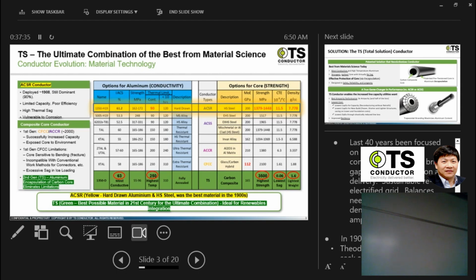And the other issue related to this limited stretching is it is a very delicate material that you have to manage your bend angles, the sheave wheels, the conductor reels very carefully. Because if you have excessive bending, you will be snapping the composite material. And that is a very bad situation to be in. And the material is also very expensive. We're talking about ceramic fiber about 10 times the cost of carbon fiber typically. And if you compare it to aluminum steel, there's no comparison.